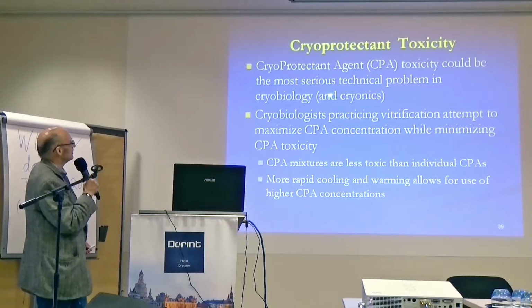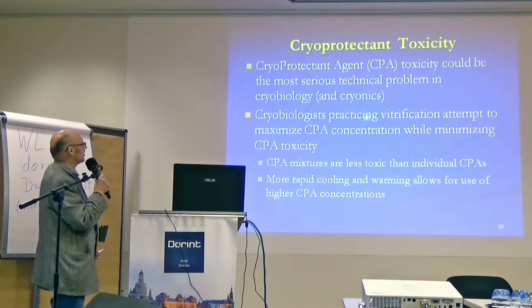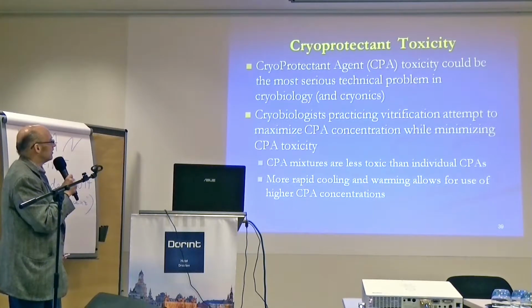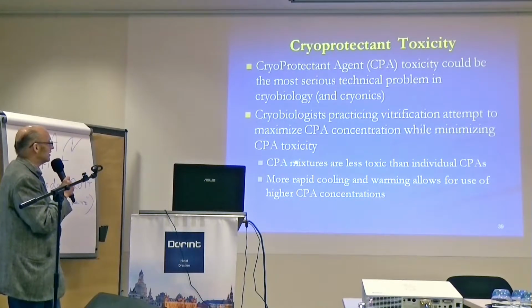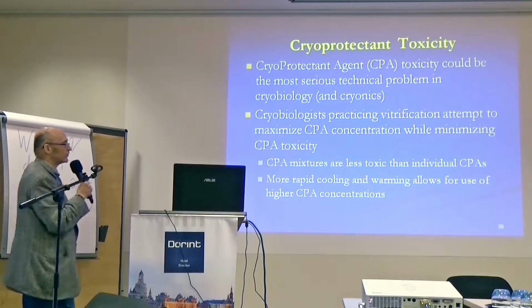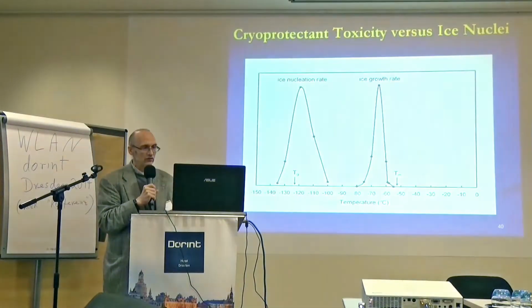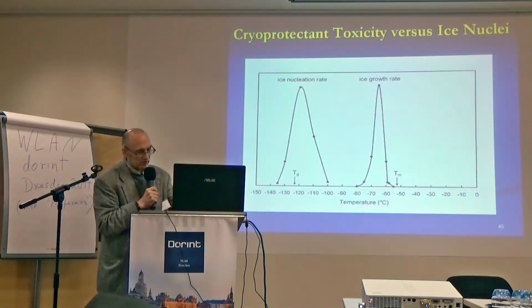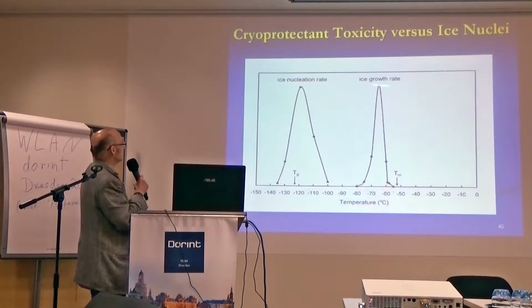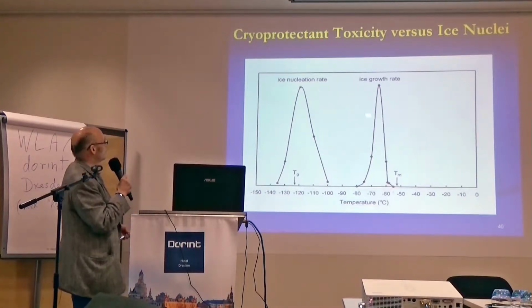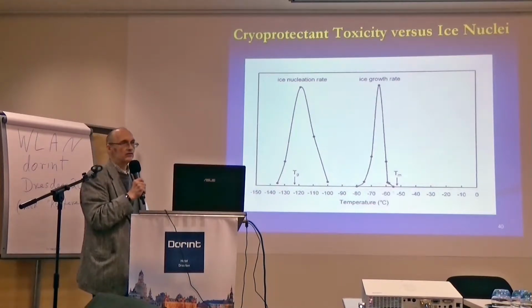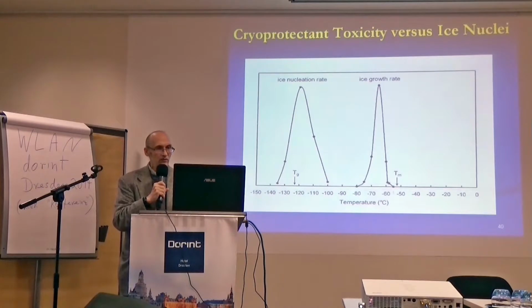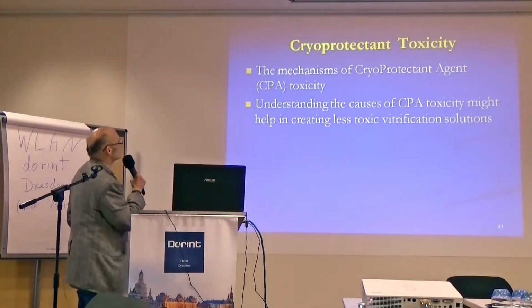So, cryoprotectant toxicity: this could be the most serious technical problem in cryobiology and cryonics. As I mentioned, we're trying to maximize cryoprotectant concentration while minimizing the toxicity. Mixtures are less toxic than individual cryoprotectants, and more rapid cooling and warming allows for the use of higher concentrations. And there's our graph again. And this whole ice nucleation problem would go away. There'd be no ice growth, no ice nucleation if we could use plenty of cryoprotectants, and if we figured out how to make them non-toxic.